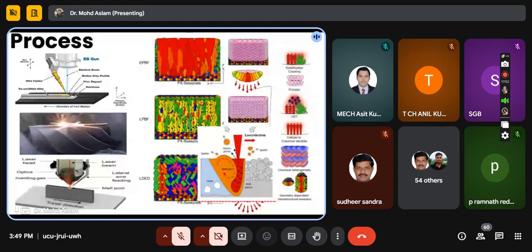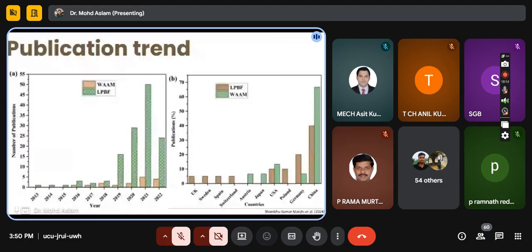So here we can easily see electron powder bed fusion has a smaller grain size and is well settled. In the case of the laser powder bed fusion method, we can easily see it is lesser compared to electron beam. And after that, in the case of the laser directed energy deposition process, there is mixing. So this is the publication trend up to 2023.